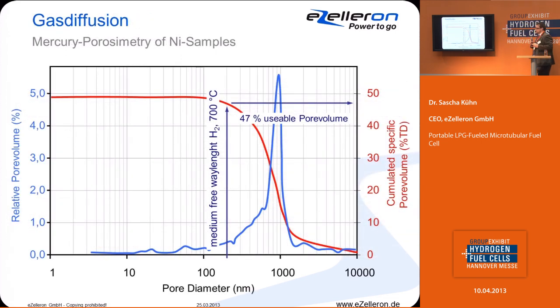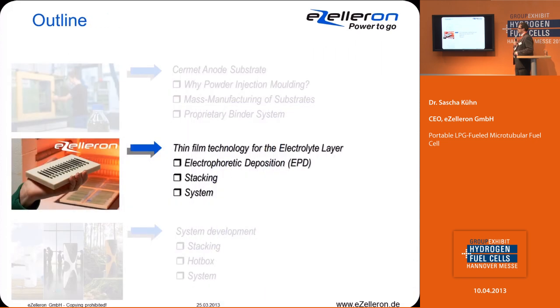The substrates have to be developed in many ways, not only the perfect structure, but also the perfect microstructure, which is important because for hydrogen you need a usable pore volume which has to be above the mean free path of hydrogen at operating temperature. This means you have to come up with a substrate with very high porosity, but not too high, because you also have to include the electronic conductivity in the substrate.